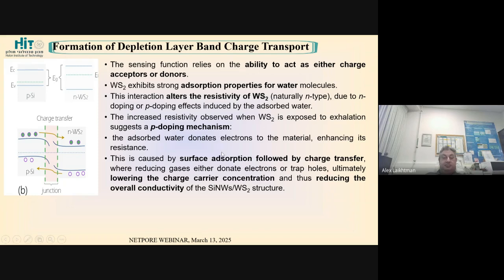And this is followed by charge transfer, and then this water absorption reduces the overall conductivity of this hybrid structure, and in such a case, we obtained much better sensing capabilities of silicon nanowires spin coated with WS2 nanostructures than in the case of just bare silicon nanowires.